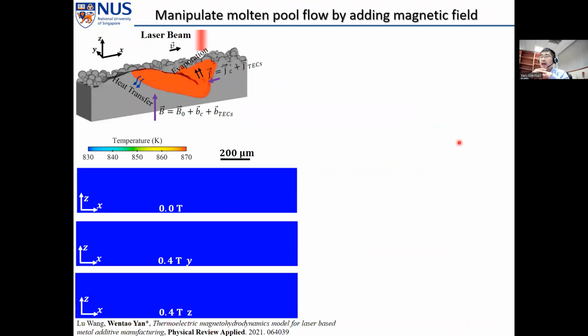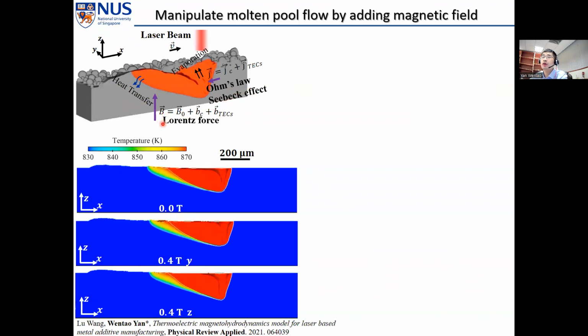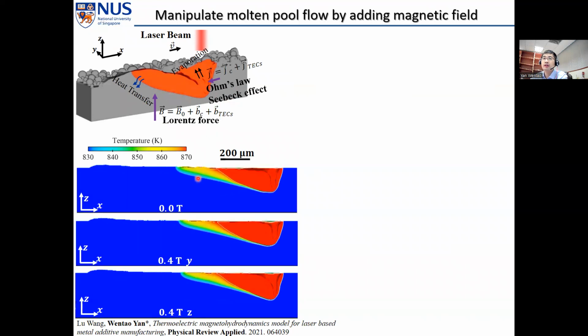And the next question is, how can we eliminate the keyhole pore or manipulate the molten flow? One popular approach is to add an external magnetic field. It has proven very effective in experiments, but the understanding of how it works is still lacking. So here we developed our model to incorporate the effect of the magnetic field through Ohm's law, Seebeck effects, and then the Lorentz force within the molten pool. We simulate different cases: without magnetic field, 0.4 Tesla along the y direction, and 0.4 Tesla along the z direction.